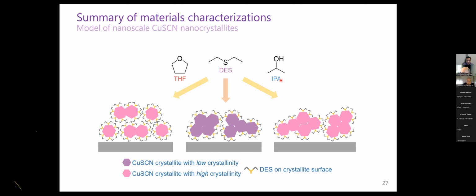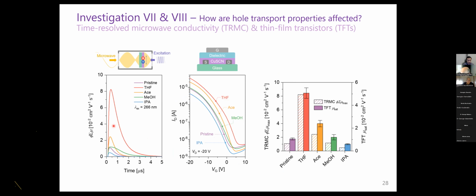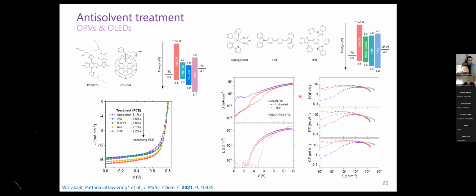Some of the treatments didn't work because IPA, for example, actually induces more aggregation. And this one here on the left gives films with high mobility. The mobility is studied with both time resolved microwave conductivity and thin film transistors. And both gave consistent results that the THF treatment can increase the hole mobility by about 4 times, basically. And we did follow-up work and also explored the applicability of this method in OLEDs and OPVs as well. And we also found that the device performance became better, like the PCE.